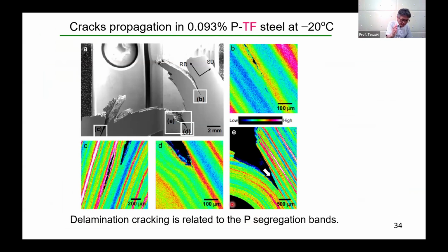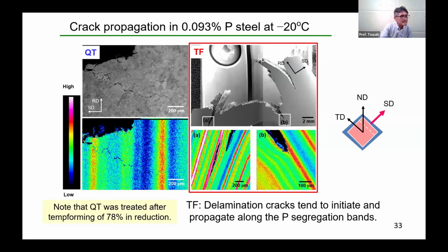But Professor Tsuchiyama, please understand that the texture is 110 parallel to RD, a deformation texture. Along the rolling direction you have 110, so no 100. No cleavage plane normal to RD, so all planes normal to RD are ductile. Of course there are some cleavage fracture surfaces in these steps also, but in some parts we can see dimples. Yes, very interesting, even in the high phosphorus steel. Thank you very much.